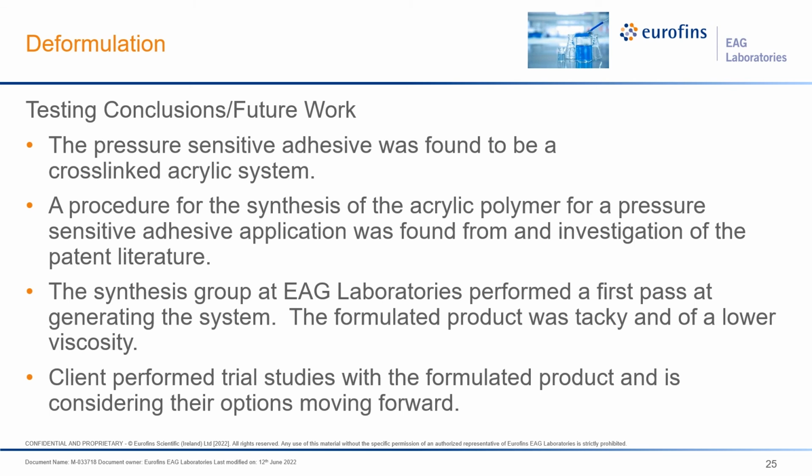Conclusions and future work for this deformulation include: the pressure-sensitive adhesive was found to be a cross-linked acrylic system. The 3 tests that we previously discussed showed that to be true. A procedure for synthesizing acrylic polymers for pressure-sensitive adhesives was identified through an investigation of the patent literature.